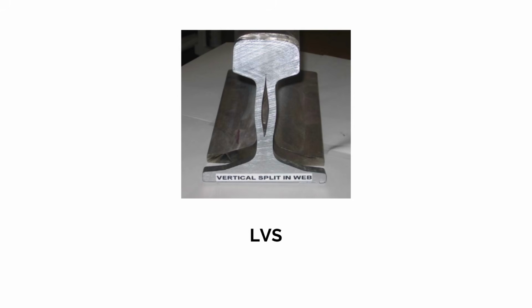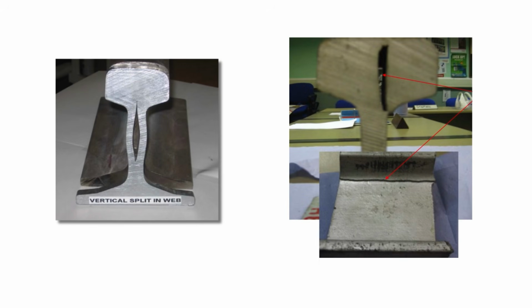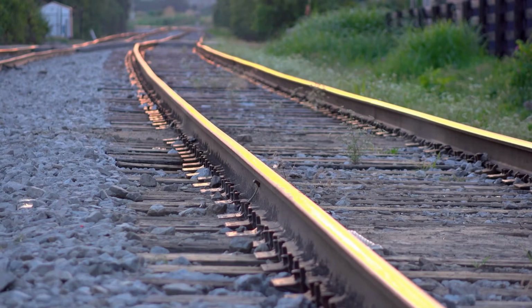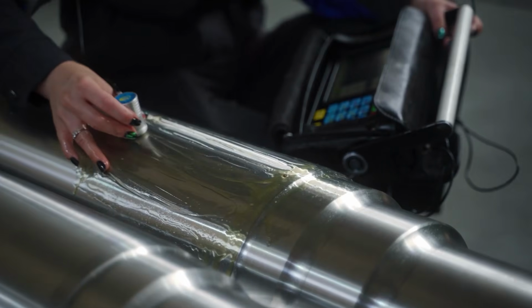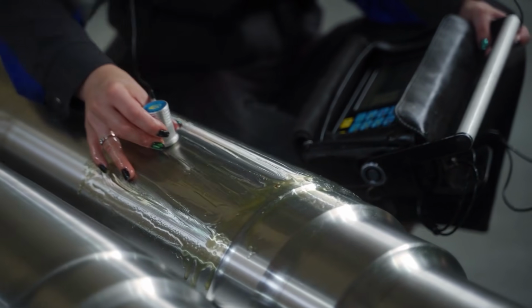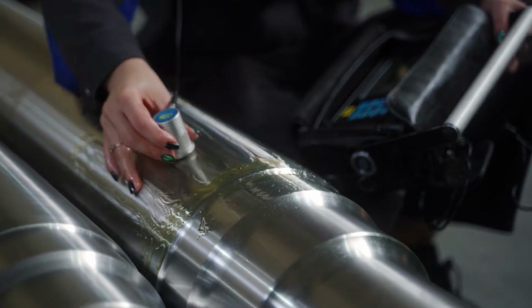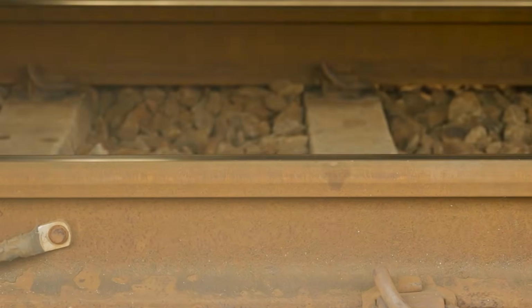Another internal defect is LVS, caused by excessive hydrogen. This leads to internal cracking in the rail web along the rail length. In rare cases, this can even cause a slight bulge in the rail web itself, but it's not something you can rely on seeing. What makes internal defects such a risk is that they can remain completely hidden to visual inspection, only detectable via ultrasonic inspection. They start off small, even by microscopic standards, but grow under the repeated stresses of passing trains until they become big enough to cause a problem.